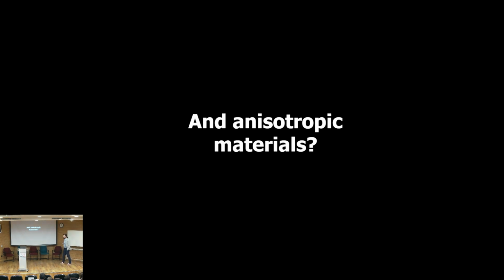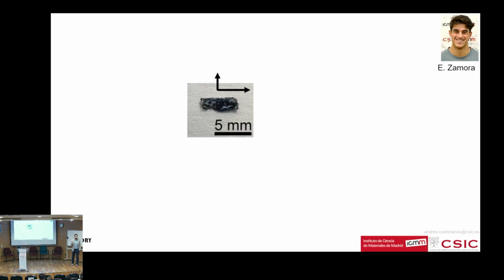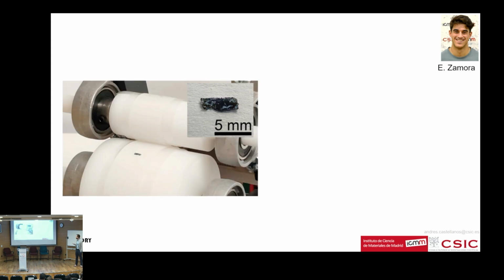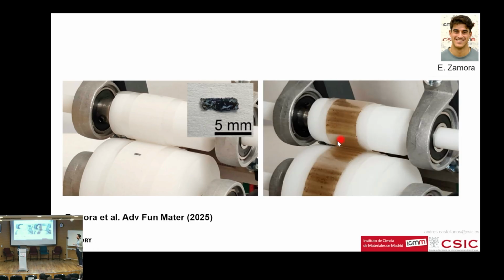Okay. Another interesting thing that we found during this work is that because this rolling mechanical exfoliation process doesn't involve any twisting forces, if your starting material is an anisotropic van der Waals material, like in this case a black phosphorus single crystal, you can already see from the single crystal that it has two different crystal orientations. Black phosphorus has this kind of elongated shape of crystals. Now you place this elongated single crystal carefully on the tape, only one single well-oriented crystal. And when you do the roll-to-roll, what you get is a film of little flakes, but all of them are aligned along the same crystallographic orientation, okay?